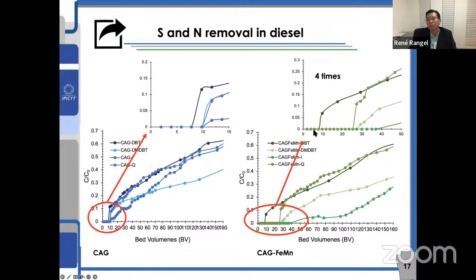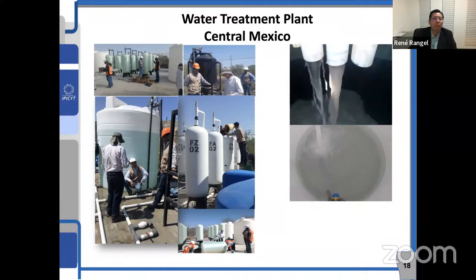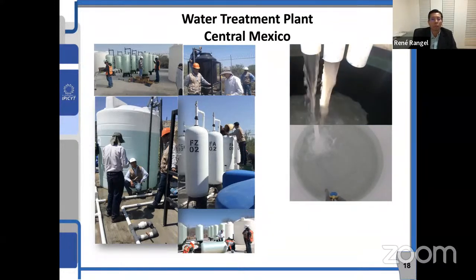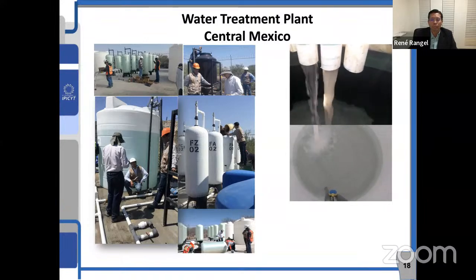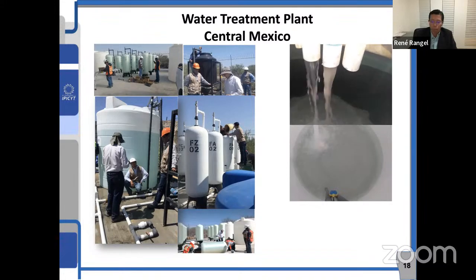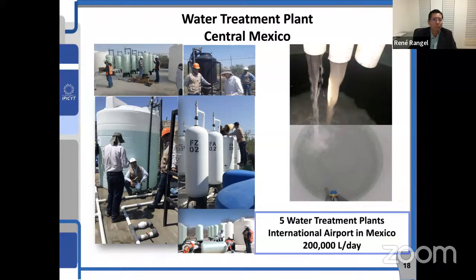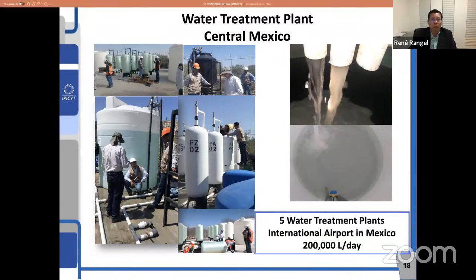In this case, the initial vector, you see, was shifted even to close to 40 bed volumes. So 4 times more sorption capacity, just by including, again, metal oxides like iron. So that's important. And this technology, we have even applied it at big scale to decontaminate water with hydrocarbons like diesel. So we have installed so far 5 water treatment plants, mainly at international airports, that treat 200,000 liters per day.